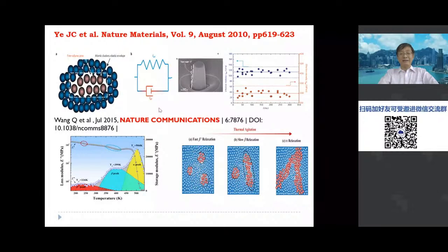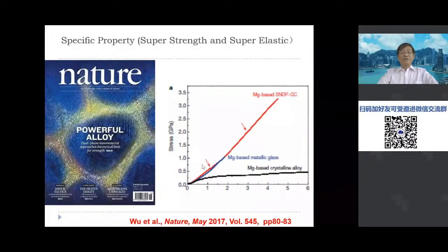So basically, we have developed the dynamic micropillar test and a mechanical test that can identify the fast beta relaxation inside of the metallic glass. What we demonstrate is the fast beta relaxation can indicate to us the state of the heterogeneity at the atomic level and how to generate this shear band. Then, after all this study, we came up with a special material, which is a dual phase super nano material.